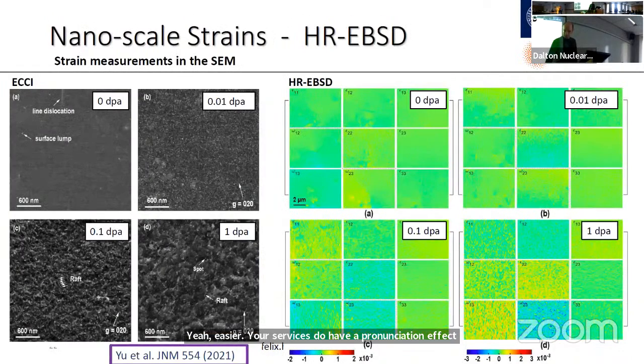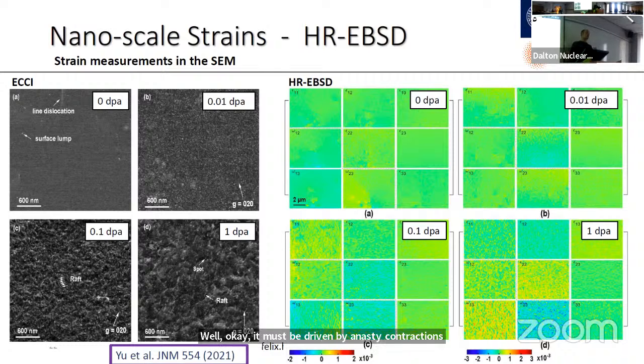The next question is then, what drives this defect organization? And our rationale was to say, well, okay, it must be driven by elastic interactions between loops, so we should be able to see self-organized strain fields. So the first go we had at measuring these strain fields was using a technique called high-resolution EBSD, where you take EBSD patterns in high resolution from your sample, and then use cross-correlation to look at the very small distortions between them to work out what the strain field is.